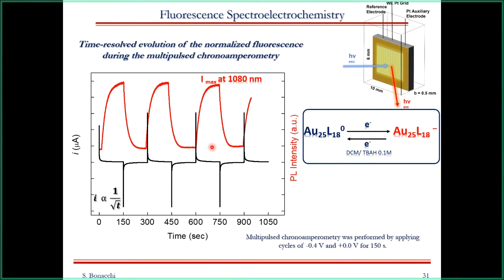We also performed time-resolved spectroelectrochemical analysis to prove the possibility to switch between the neutral form and the -1 form, and for this purpose we performed multi-pulse chronoamperometry measurements. As you can see, there is a perfect match between the current density and the emission, which can be switched on and off if you look at 1080 nanometers. So you can really switch the emission of the neutral form in the near infrared region in real time. This work is ongoing, but it is the very first example of spectroelectrochemical analysis of this kind of cluster in the near infrared region.